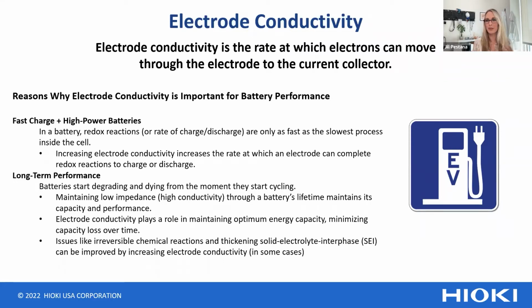We can't control the entropy inside of the cell as reactions take place, but we try to control it as best as possible. And by controlling, I mean, we want to keep the impedance of the cell as low as possible for as long as possible during the cycle life of a battery. And low impedance or high conductivity maintains the battery's capacity and performance. Electrode conductivity plays a role in maintaining the optimum energy capacity, minimizing capacity loss over time.